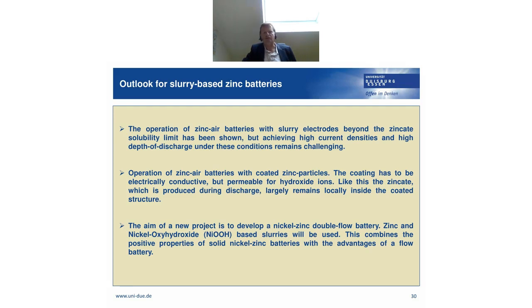So one approach that we will take within a funded project soon is operation of zinc air batteries with coated zinc particles. This coating has to be electrically conductive but permeable for hydroxide ions, of course. The hydroxide ions have to diffuse through the coating and then react with the zinc to yield zincate. Like this, the zincate, which is produced during discharge, largely remains locally inside the coated structure, and then it can be, or it will be, electrochemically reduced again to zinc. We have a university partner who has already some experience in applying these electrically conductive, you can say glass-like coatings.